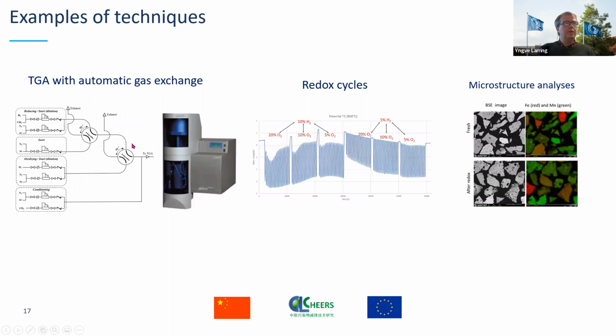The TGA is a very nice instrument where we can switch between reducing, inert, and oxidizing very fast and in a lot of different cycles. So we can have this automated, and it goes in this case, which you will see later on, between high hydrogen concentration and low hydrogen concentration, and also different oxygen concentrations, to look at how active it is under a CLC process, which has different conditions on the inlet and outlet. We also did some microanalysis to see, for example, whether the iron and manganese are mixed or separate particles, and such things as well, to get an overview of how the sample is.